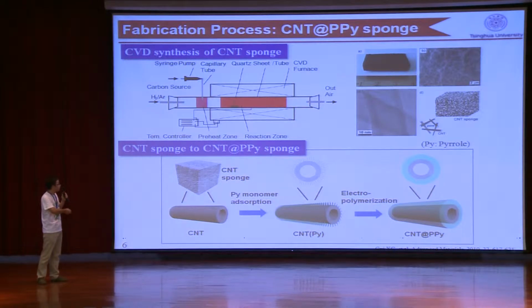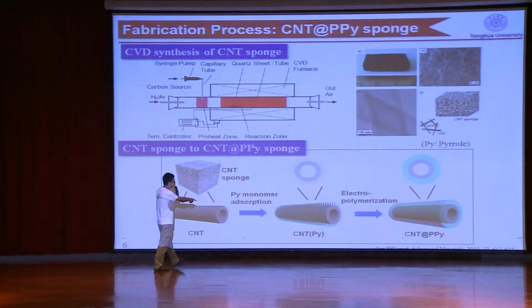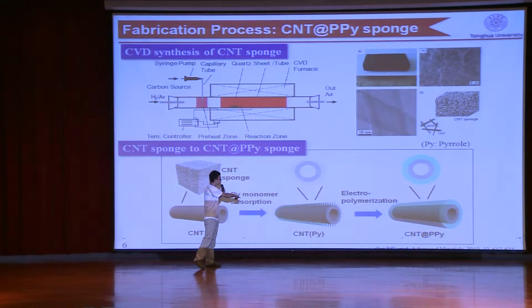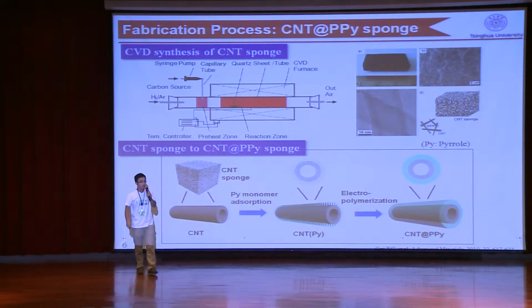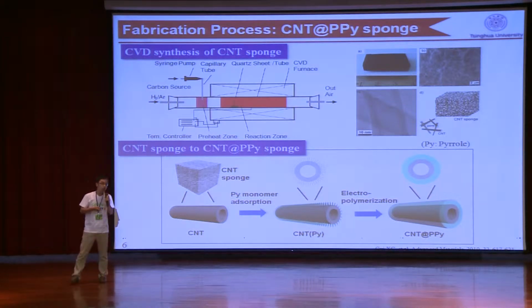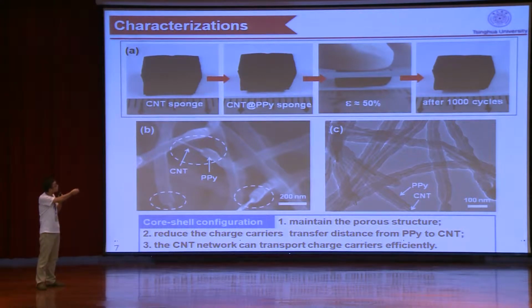This is the process. We directly immerse the CNT sponge in PY solution to absorb PY monomers on the CNT surface, and then through electropolymerization, the PPY monomers will cross-link into a uniform PPY layer and result in this core-shell sponge. From the figure, we can see that after PPY deposition, the sponge can maintain its original shape, and it can be compressed to large strains without breaking or collapse. And even after 1,000 compression cycles, it can recover to its original volume.